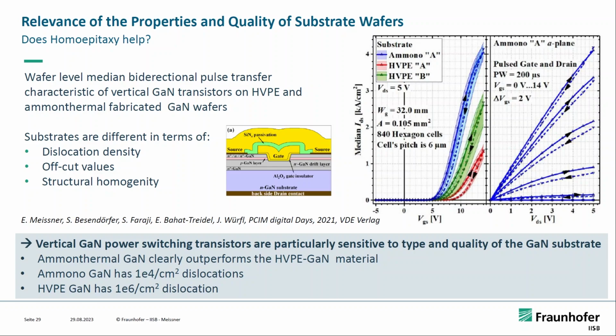This, for example, is in collaboration with colleagues from FBH in Berlin, who measured power transistors made on gallium nitride substrates. You see here N-type gallium nitride substrates, and a plot of the median here and the gate source voltage. The blue, green, and red curves - the green and red are HVPE material, and the ammonothermal material is blue. But in fact it's all gallium nitride, pure gallium nitride substrates, yet they behave differently - and it's not a slight difference, it's a remarkable difference.